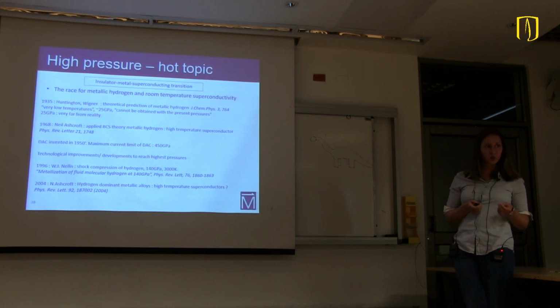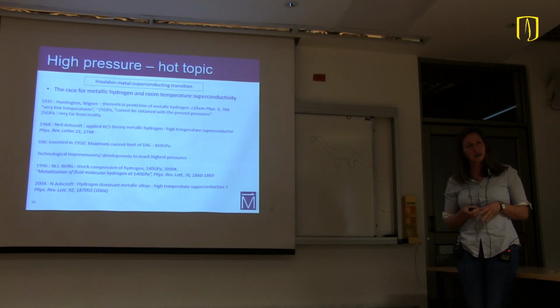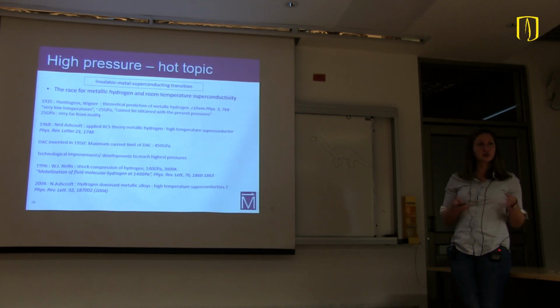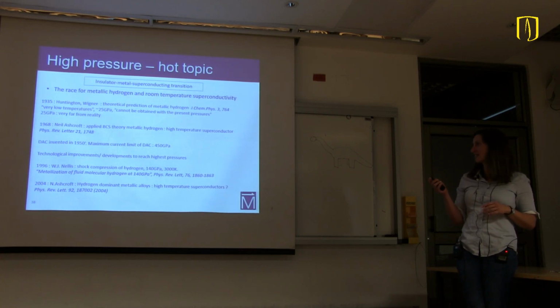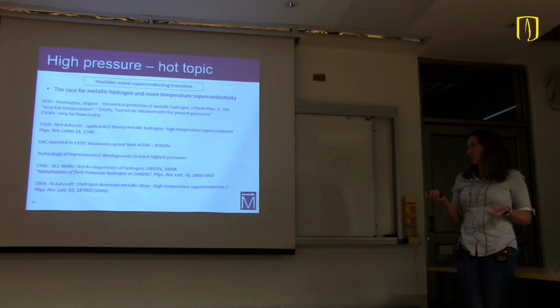Huntington and co-workers predicted hydrogen to become metallic. They had no idea what the pressure would be. So they said, well, it's 25 GPa or higher. And in 1935, we couldn't go that high. We could go in kilobars or so. It turned out to be very far from reality, and actually not much work was done then.